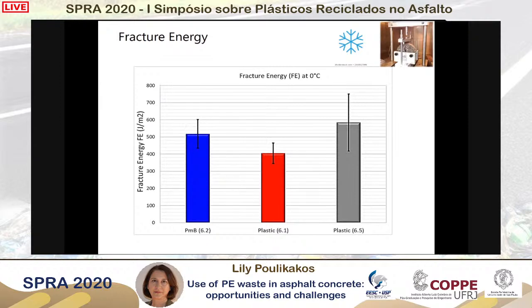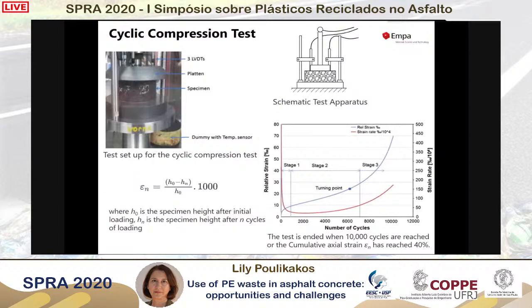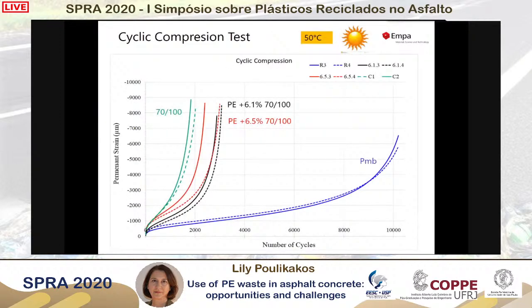So I can say that in general, we could reach the low temperature cracking performance of the polymer modified mixture. And if we look at the high temperature performance, we've used the cyclic compression test, which registers the strain in comparison to the number of cycles. If you see the blue curve, after a while the deformation becomes so large that the increase becomes exponential. So we basically like to move this turning point towards the right-hand side of this diagram. Now, these are the results that we have. First of all, in green is the mixture that used the straight run bitumen, and the red and the black are the ones that had PE in them.